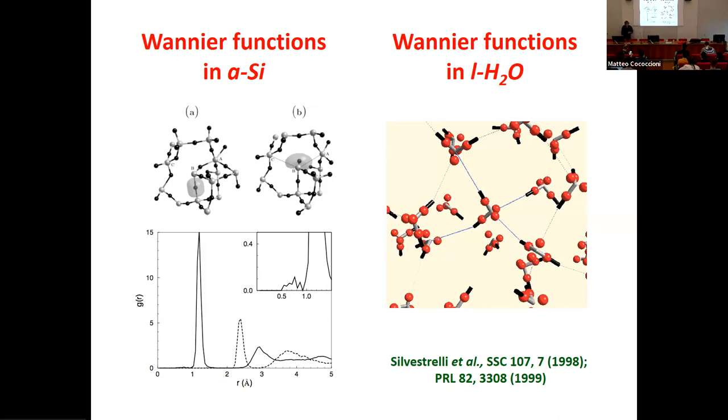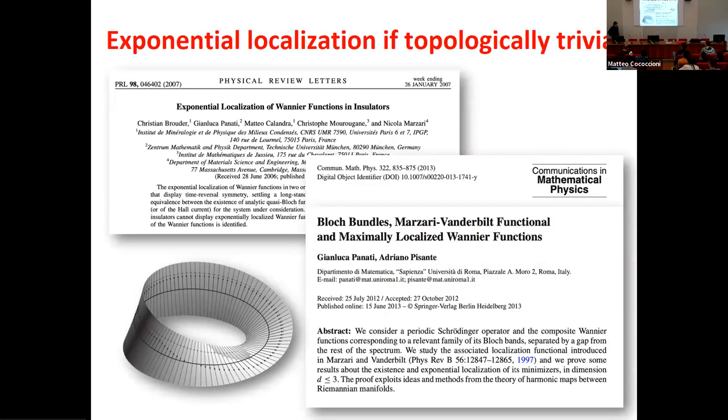And what was very important was that we were showing that there was not a one-to-one correspondence between an electronic defect and a geometric coordination. So you could have, say, states that look fourfold coordinated from a geometric analysis, but in reality, maybe one of the Wannier functions was not spanning a covalent bond as fourfold coordinated silicon should do, but was much more looking like a lone pair.